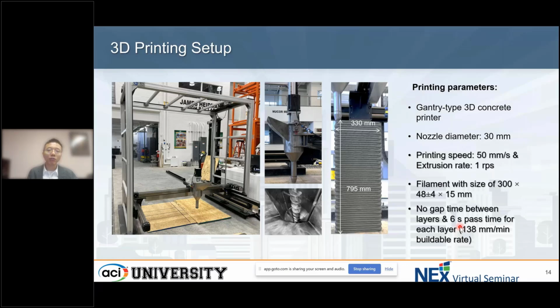And the vertical buildable rate is pretty high too. It's around 138 millimeter per minute, so it's around 8 meter per hour. And then we print the mixture until it failed. And we just print a single layer, as this figure shows here, with around 330 millimeter length. And I will show two videos. The first video is when plastic collapse happened and the bottom layer deformed. So when the failure happened, we recorded the maximum buildable height. And the second one is elastic buckling.